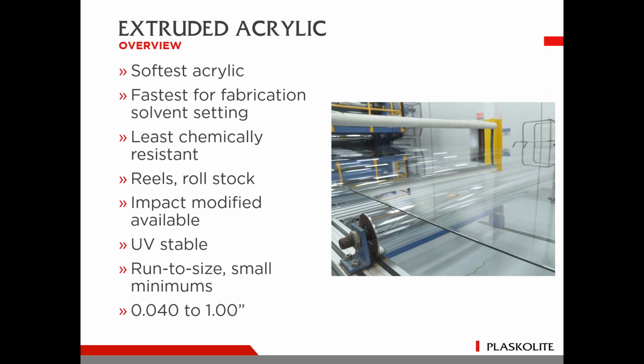The acrylic products in general are all UV stable, but some of the neat things that we can do with some of these are we can do very small run to size minimums. So thin gauge and run to size are two of the things that you should be thinking about when you're looking at some of the different acrylic products, especially with PLASKOLITE being able to do them at 1,000-pound minimums. It's really pretty attractive to do. So from 0.040 to 1 inch thick sheet for extruded.